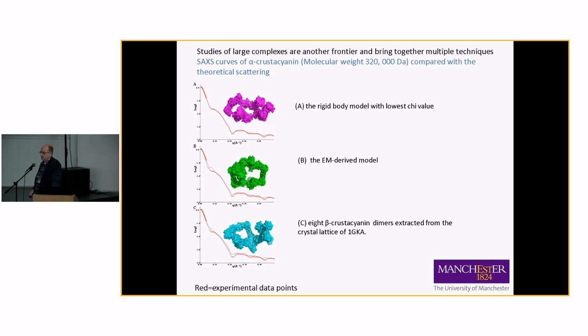So as an example, the alpha crustacyanin, which is the eight of the beta crustacyanins, we could not grow quality enough crystals of the alpha crustacyanin. It's 1/3 of a million molecular weight, and so I think we had 10 angstrom resolution diffraction spots, but we couldn't get a unit cell even, and so that's why we turned to EM and solution X-ray scattering and came up with these models. And then after this time, the cryo-EM improved quite a lot.